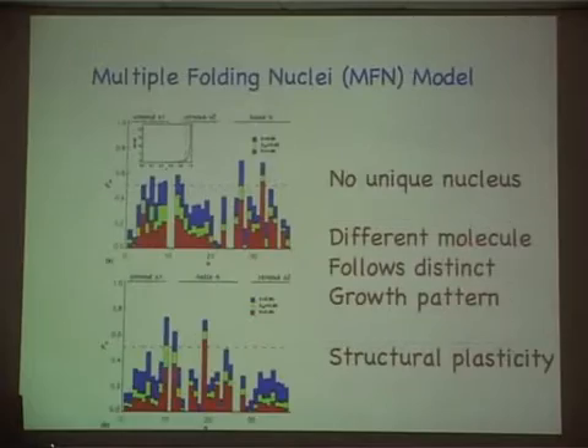So we know this. That implies, and you can do this hundreds of times, that there's a large heterogeneity in the folding trajectories, which means that whatever processes govern the formation of this structure at this end in this trajectory have to be somewhat different. And if this is quote-unquote nucleation in some sense, the nucleus that you would identify in this trajectory is different from a nucleus identified in that trajectory. And of course, a nice way of saying this is there is no such thing as an average protein. Every protein molecule is in fact special. So it's that specialness that we want to tease out in doing these sorts of trajectories.